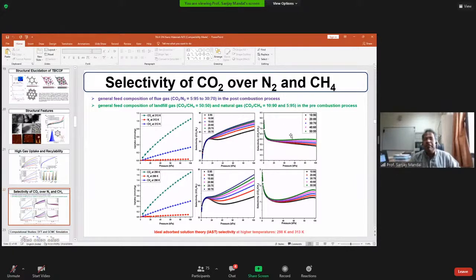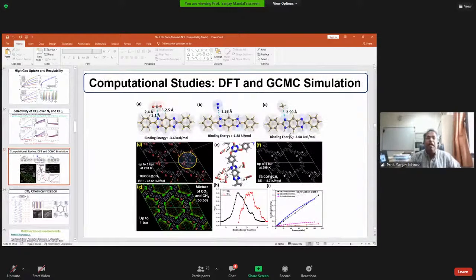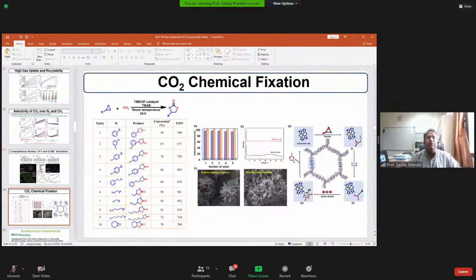Similarly, we have the same thing. So this shows that our material can do it. We have done some DFT calculations and GCMC simulation, and we can tell you exactly what is going on. Briefly, I can tell you that the binding energy for CO2 is much lower than that of methane, and here is the selectivity again for 50-50. So in this interaction mode, you see that CO2 binds pretty well.